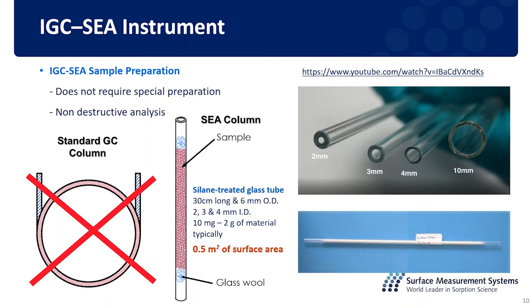And the sample preparation for the instrument is rather simple. We just need to put the sample inside our column, and our column is a straight 30 centimeter long column with different sizes of diameters. So we have the 2, 3, 4 millimeter diameter column for different kinds of powder or fiber material. We also have the 10 millimeter inner diameter column for some larger particle size material, like a tablet with some special coating that you don't want to break into pieces, then we will recommend to use this 10 millimeter column. And the sample amount for the analysis really depends on the surface area of the material. So typically we can use from 10 milligrams up to 2 grams of the sample for the experiment.